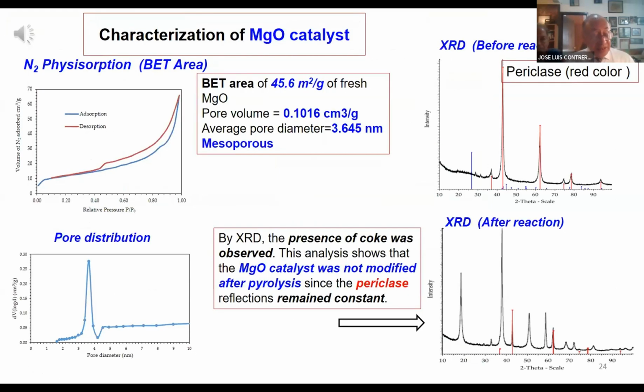The characterization by nitrogen physisorption of the unevaluated magnesium oxide catalyst showed a small area of 45 square meters per gram. By X-ray diffraction, the structure called periclase was identified. This structure didn't change after the reaction. Reflections due to carbon deposited in the evaluated catalyst were also observed.